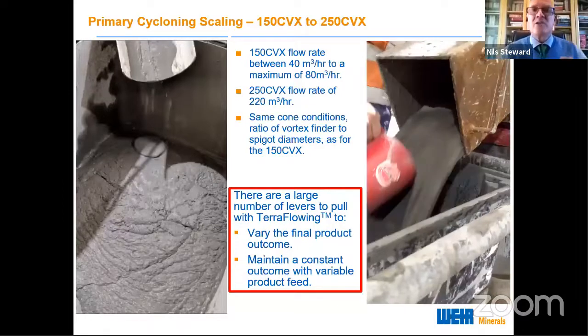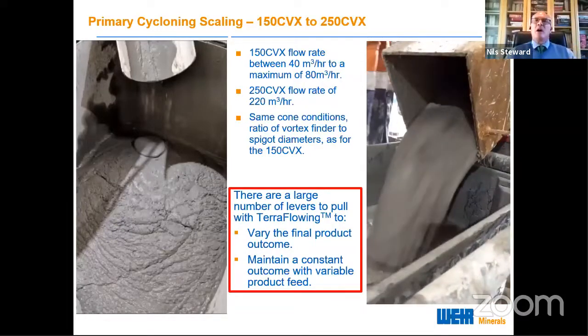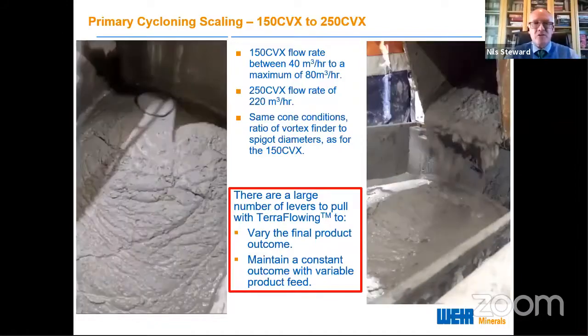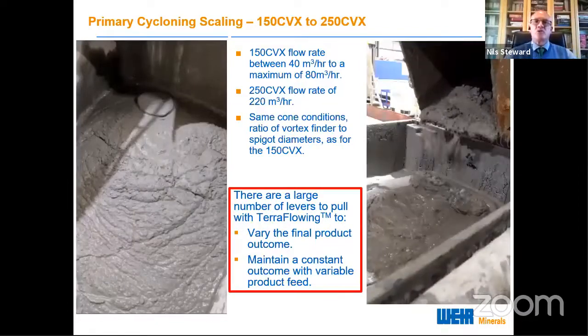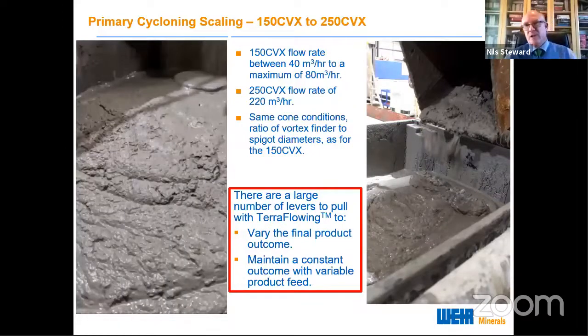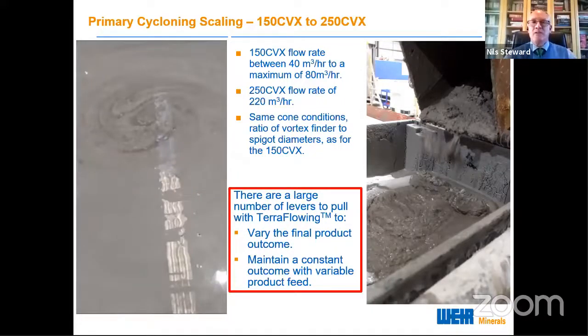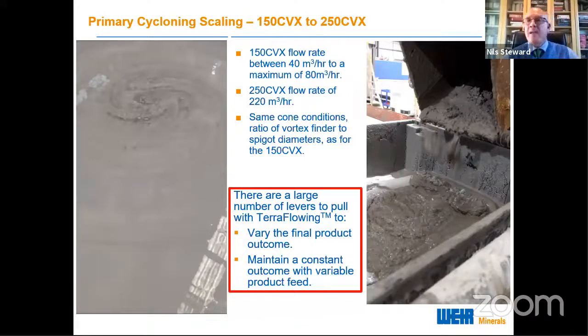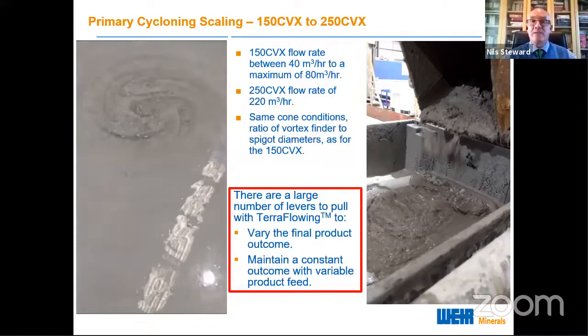We have achieved exactly the same underflow conditions of concentration and particle size distribution by matching cone ratios, which is the ratio of the vortex finder to the spigot. So we have a huge number of levers that we can pull with Terraflowing in our primary cyclone to vary the product outcome or maintain a constant product outcome from a variable feed, because we have all these levers to pull.